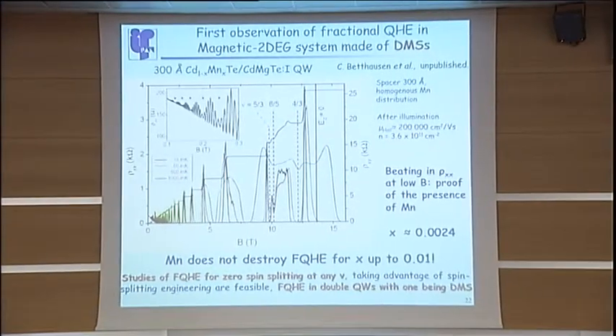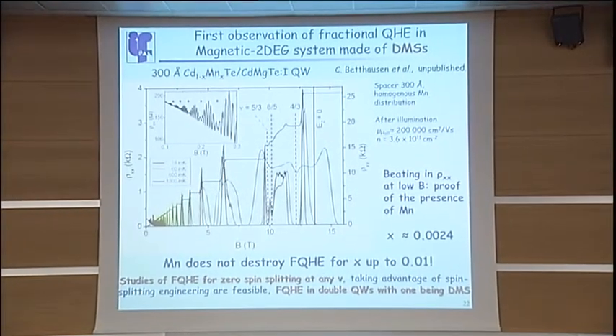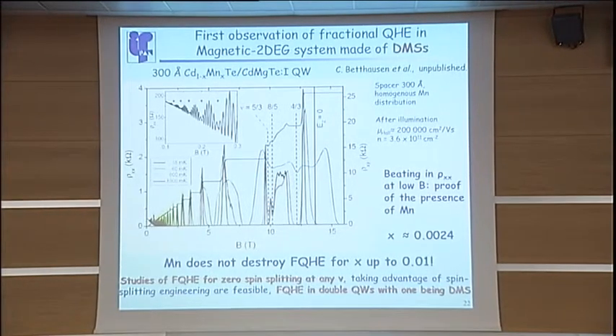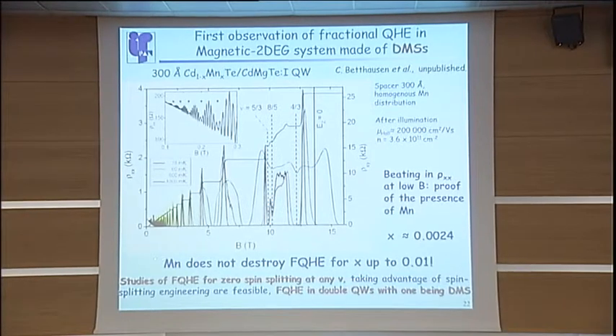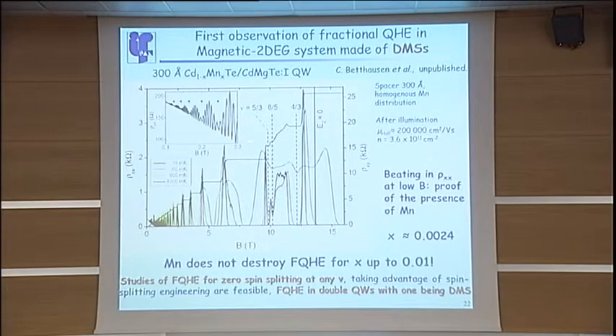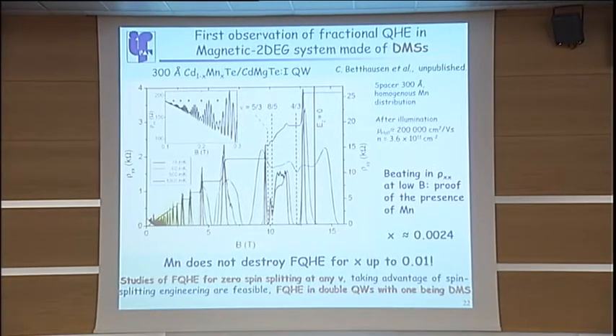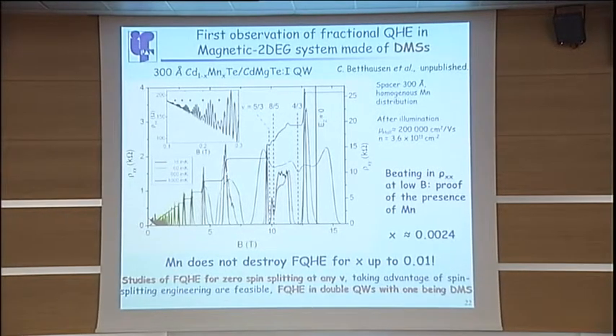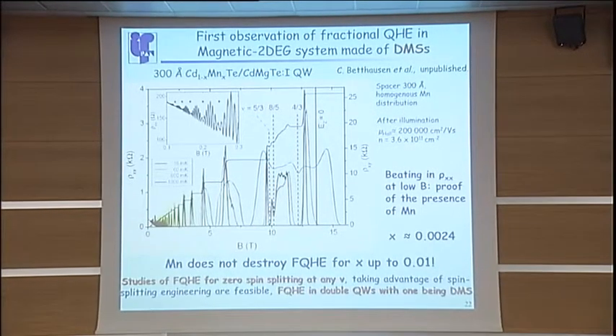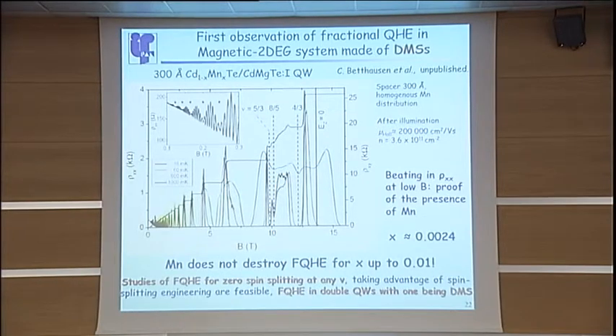Now, introducing manganese, as I was hoping at the beginning, did not introduce too much of a problem. If you don't put in too much manganese, you still observe fractional quantum Hall effect states. And we know that we have manganese inside, not only because of the growth, of course, but also because we observe this nice beating pattern at low magnetic field, which is indicative of the presence of the manganese, from which you can also determine the concentration of manganese.